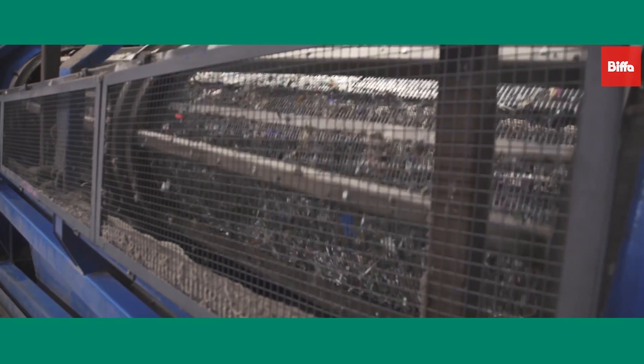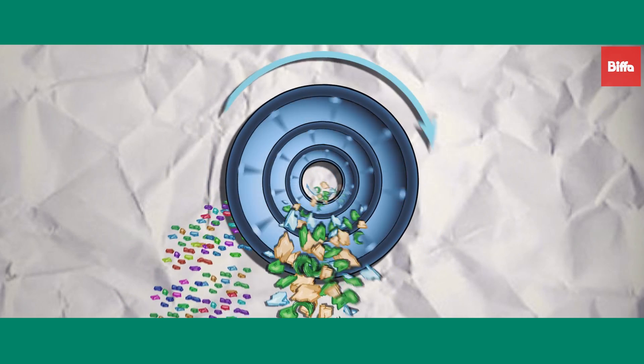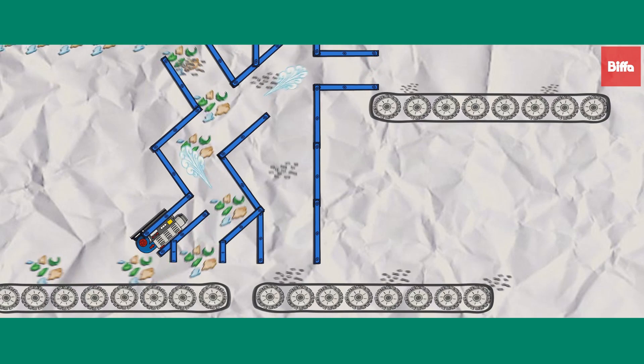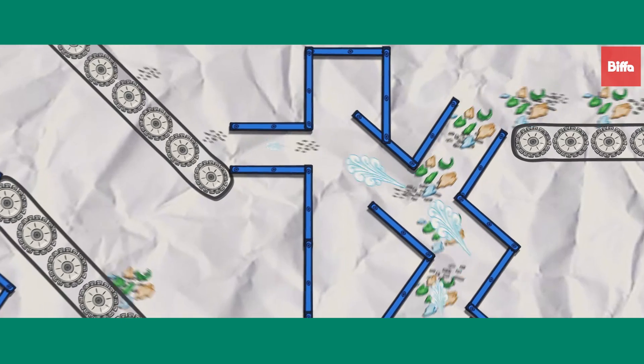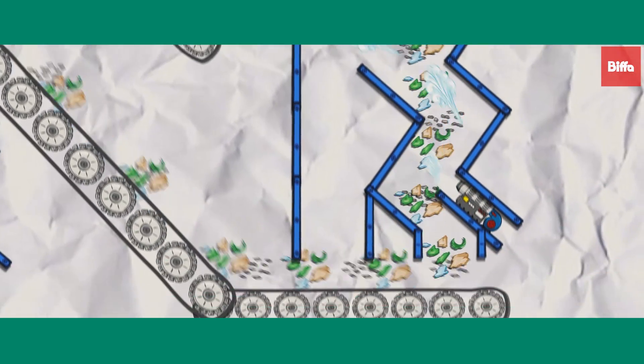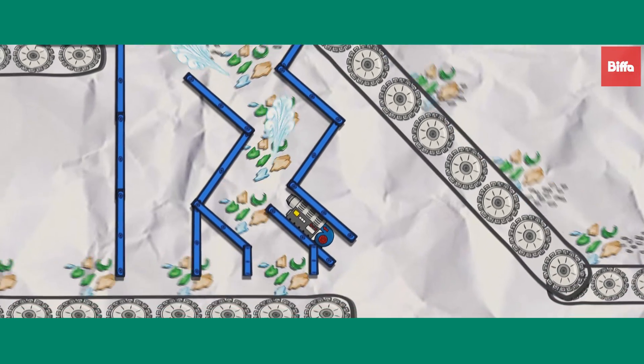The fragmented glass is transported onto a rotating trommel which separates glass from the mixed stream of materials. The smaller fragments of glass pass through a single zigzag machine which uses an air stream to remove contaminants and debris. The larger glass passes through two zigzag machines. The first removes any fibre which is pulled off and transferred back into the fibre cabin. The second is set to a higher velocity to remove as much of the remaining contaminant.